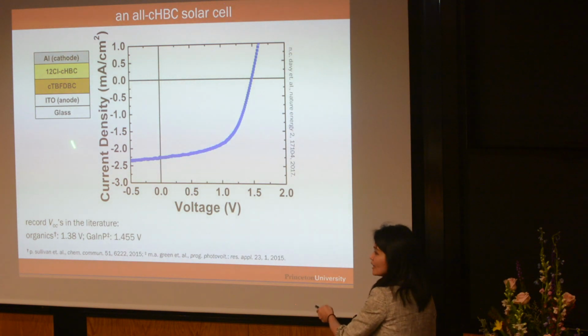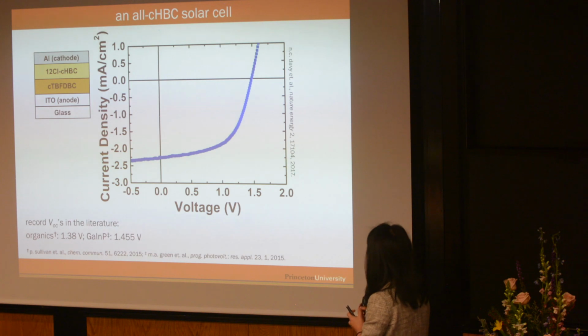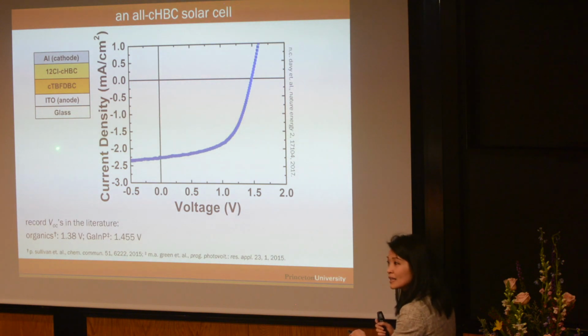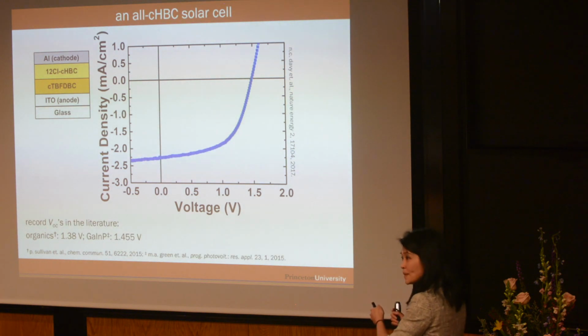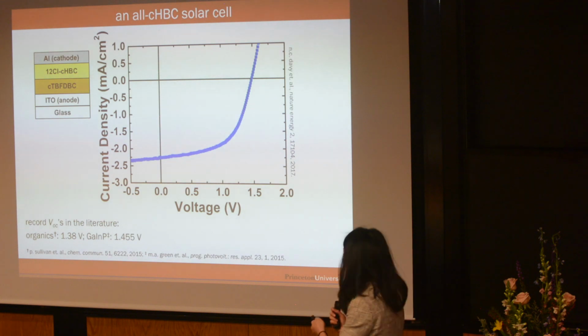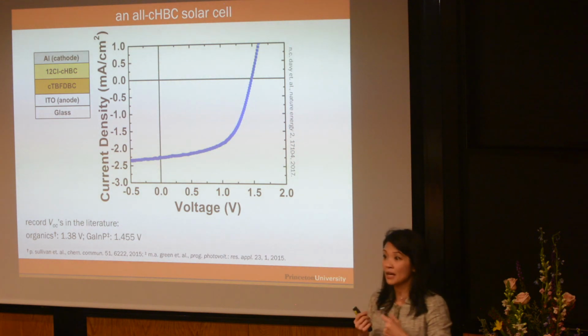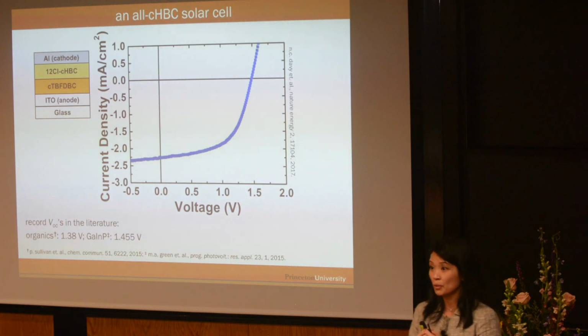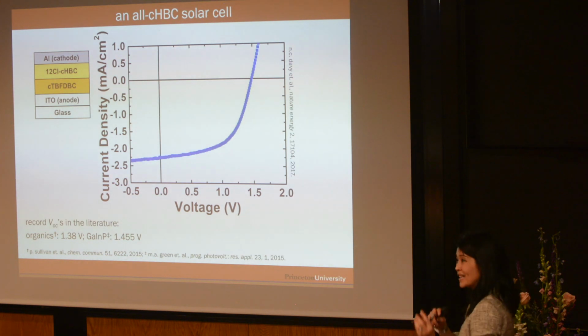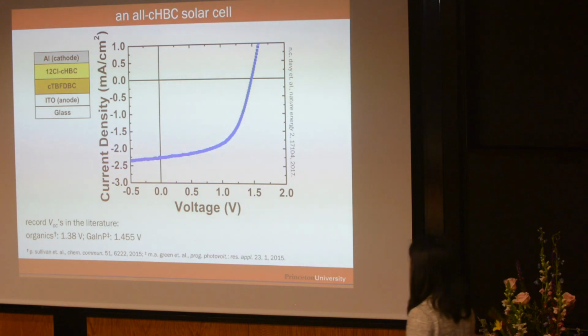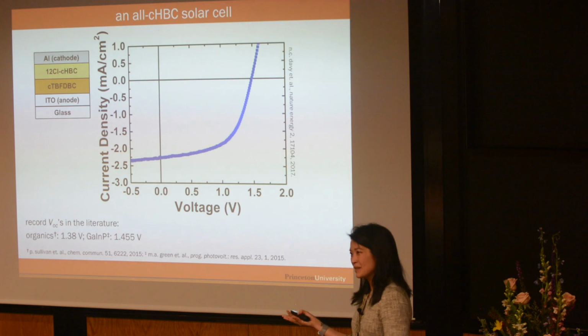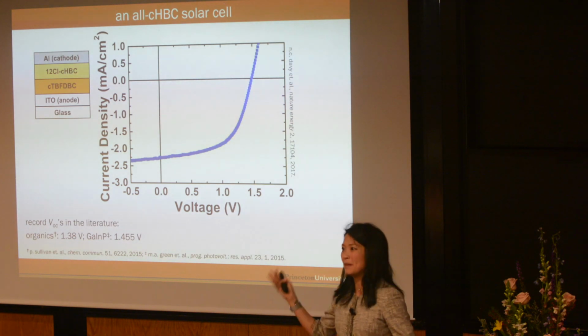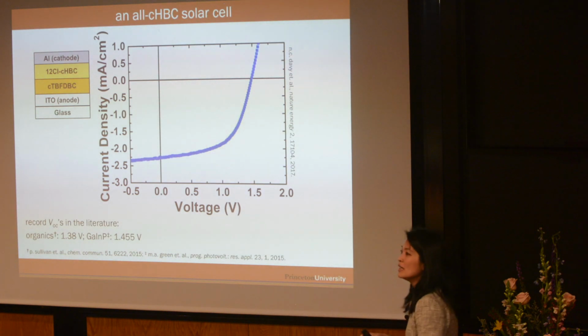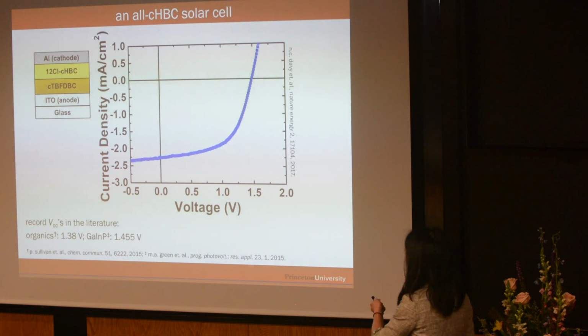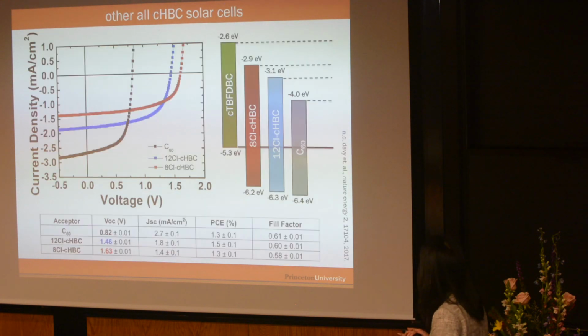So this is our device structure. It's a planar heterojunction structure. We don't get a whole lot of current, but our open circuit voltage is really high. In fact, when we first reported this, this was the record open circuit voltage that had been reported in the solar cell community, organic, inorganic, and otherwise. Again, because we're using wide bandgap materials, right? I mean, people don't think about using wide bandgap materials to do these kinds of things. So we're not getting a whole lot of current, but our voltage is really high, okay?